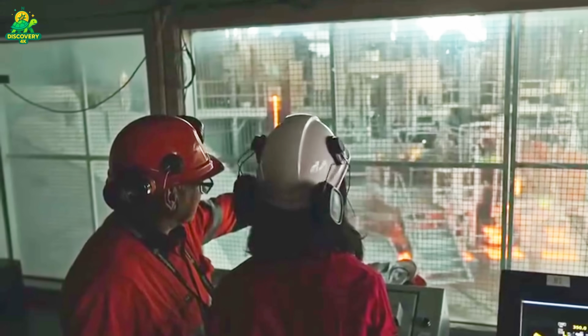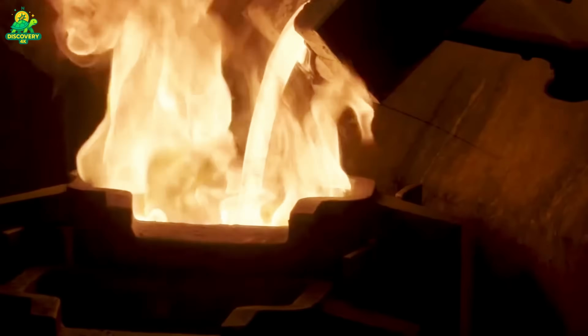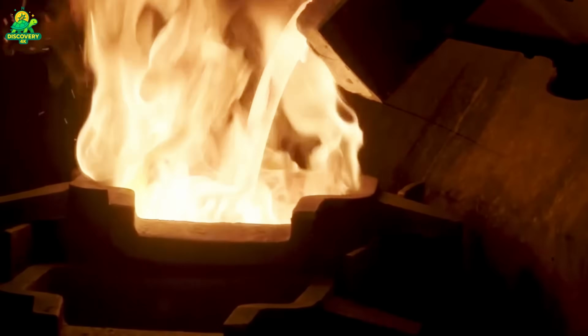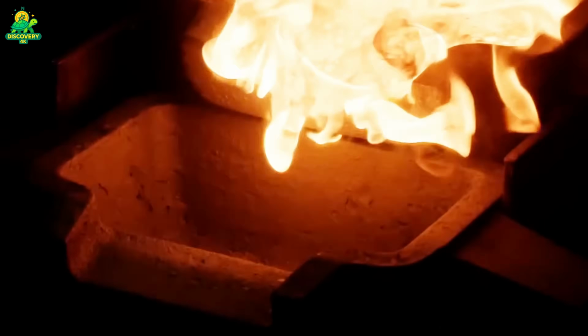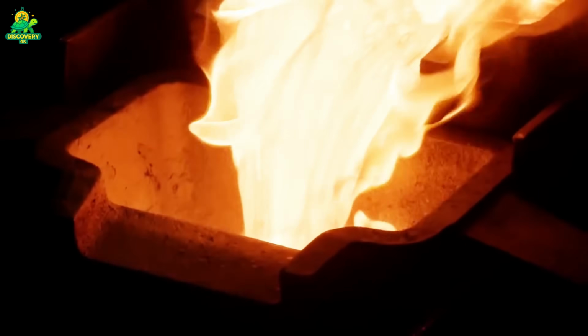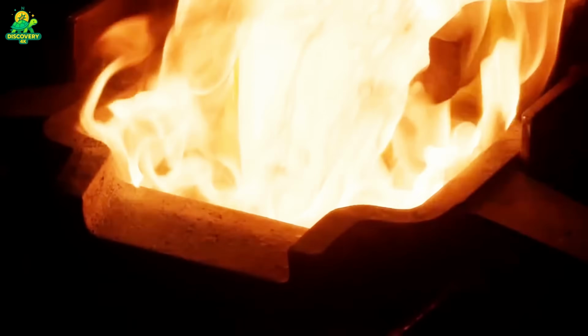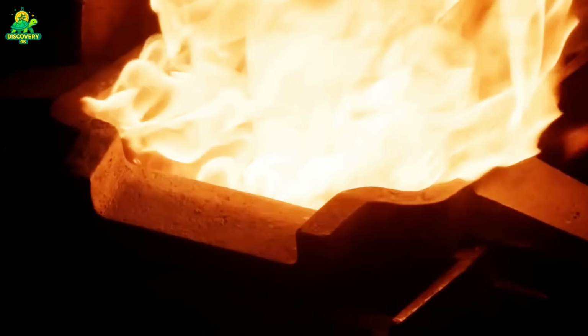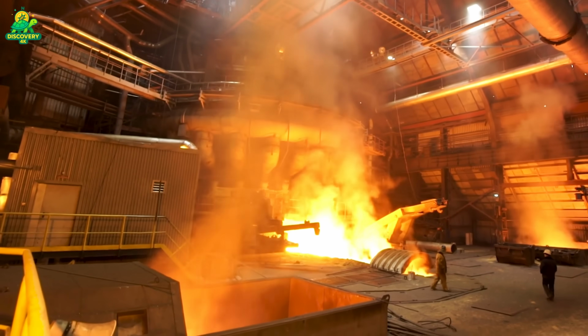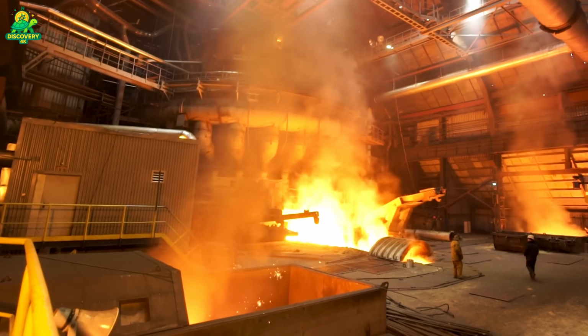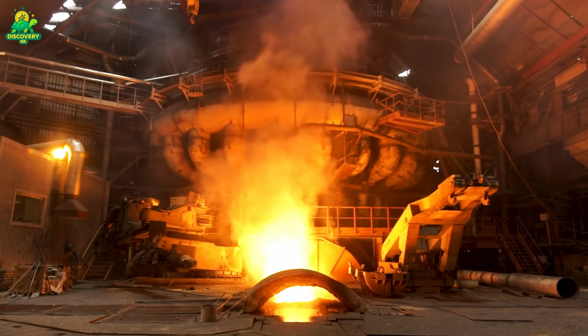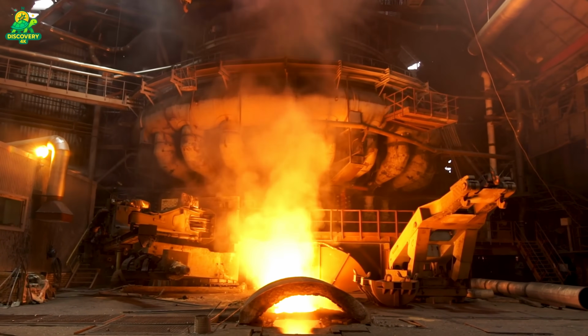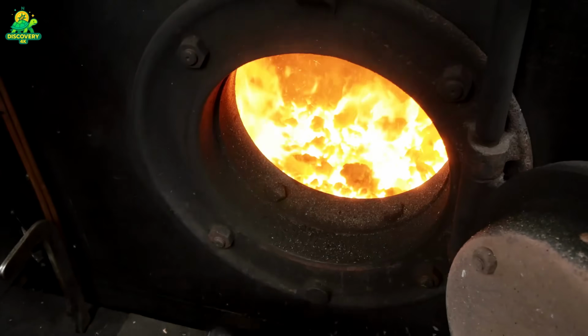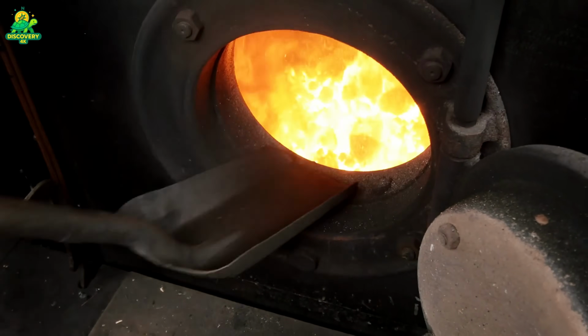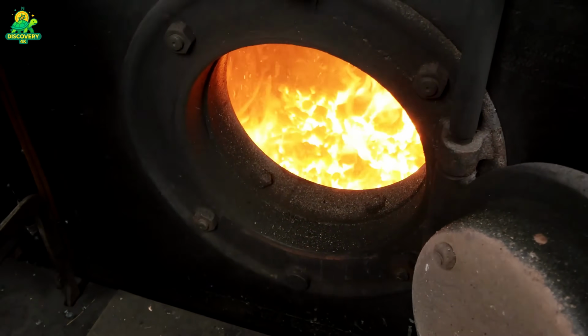After concentration, the copper-rich slurry, now upgraded to about 30% copper, travels to one of the most dramatic stages in metallurgy: smelting and refining. This is where chemistry, heat, and human ingenuity combine to transform dull concentrate into glowing, usable copper metal. The concentrate, still containing sulfur and iron, is dried and fed into huge furnaces. Imagine steel chambers large enough to hold a small house, burning at over 1200 degrees Celsius, or 2200 degrees Fahrenheit.